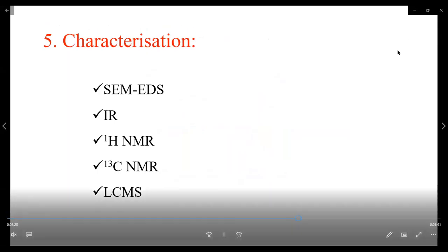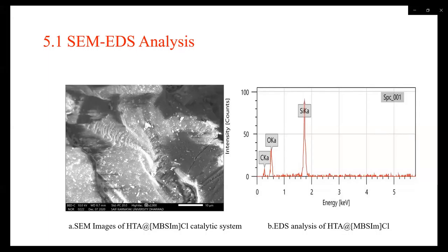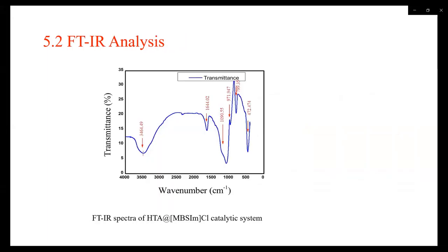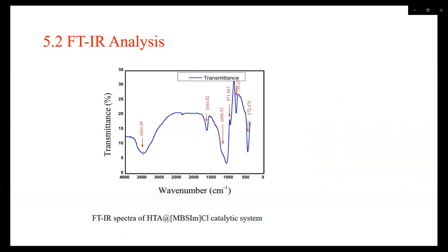Here we have carried out this characterization. The morphology of the catalytic system was confirmed by SEM, while the high concentration of silica in the catalytic system was confirmed by the EDS analysis. In case of FTIR analysis, the broad band obtained at 3464 is due to the stretching vibration of SiOH, while that obtained at 1090 is due to the asymmetric vibration of structural siloxane. The presence of the ionic liquid is confirmed from the stretching vibration at